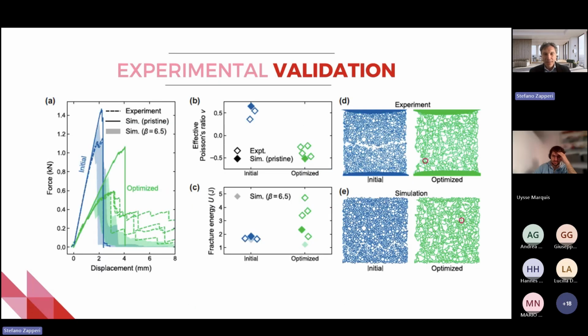Then once we've done all this simulation, we try to see whether this can be realized in practice. So we did experiments, 3D printed the structure and so on, and we can see that there's a good agreement between experiments and simulation, although they are quite different in the way they fracture. For instance, in the experiment, this exactly the same structure fractures in different places with different cracks. Why is that? Because there is a source of disorder that we cannot control, which is the disorder due to the 3D printing. Of course, you would like to print a perfect structure, but it's not exactly perfect. So you get defects that are due to the production, and this you cannot capture. So although the lattices look the same, there is an extra disorder that you cannot control that creates this difference. But on average, the properties are preserved by the experiments.